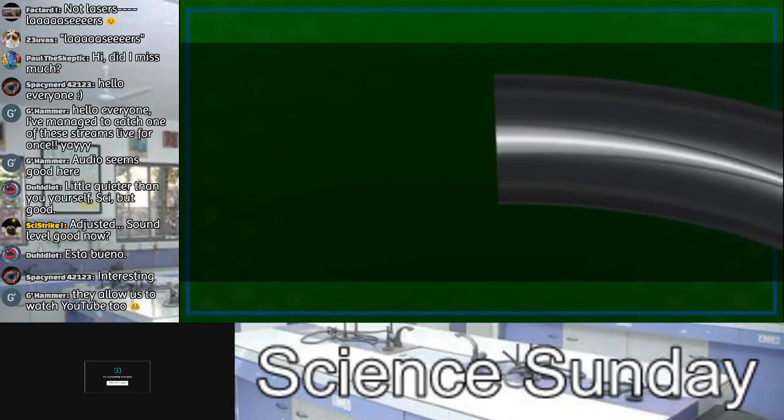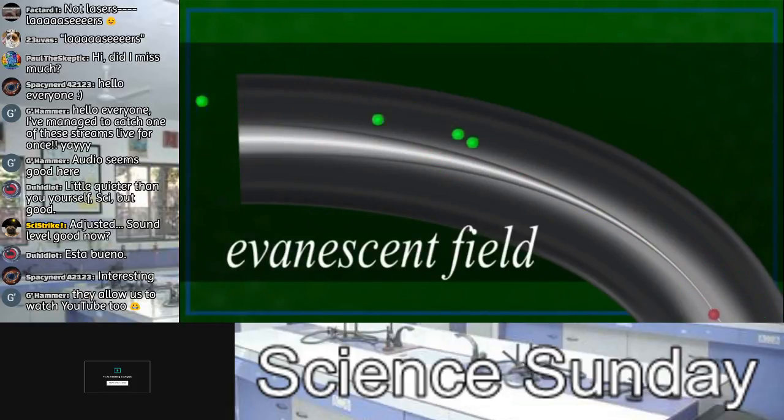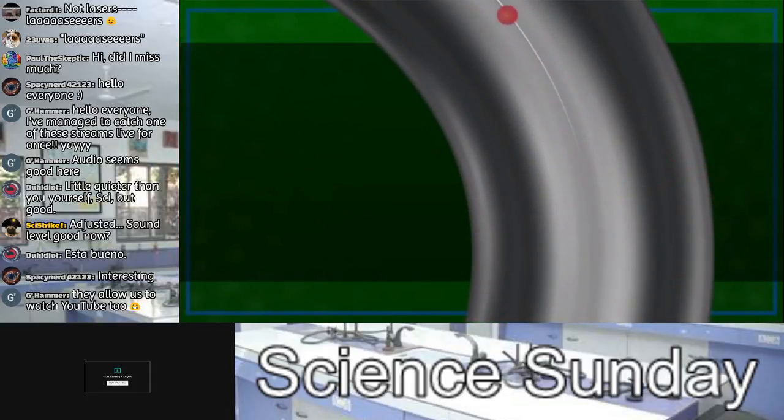The combination of a low numerical aperture in the core and a bend in the fiber allow the higher modes to escape, leaving the fundamental mode in the core. The evanescent field of the single mode beam expands to fill the core diameter, avoiding nonlinear effects. Best of all, the amount of energy from the core that escapes as a higher mode is minimal. Serious, extremely high beam quality fiber lasers were now possible.